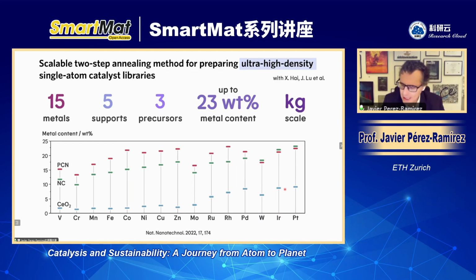It will be a breakthrough to prepare a single atom-based catalyst on an inorganic support, like an oxide, with contents of 25 weight percent. And actually, many groups are working on that, how to increase the binding sites on oxides, including our group. So we hope to make progress on that. But making ultra high density catalysts is about tailoring the carrier. That's what you have to do, because you need to produce a carrier that has this huge amount of binding sites that can be occupied by the metal precursor.